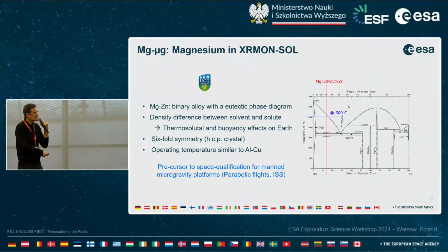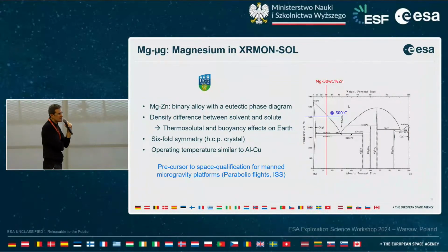Magnesium-zinc is a good candidate, and it is part of a project called Magnesium Microgravity, which has been selected for a sounding rocket after answering the previous announcement of opportunity from ESA. So magnesium-zinc is a binary alloy with a eutectic phase diagram. It's very similar to aluminum-copper in terms of phase diagram and operating temperature. There is also a large density difference between the liquid and the solid. So in the same way, we expect thermosolutal and buoyancy effects on Earth.